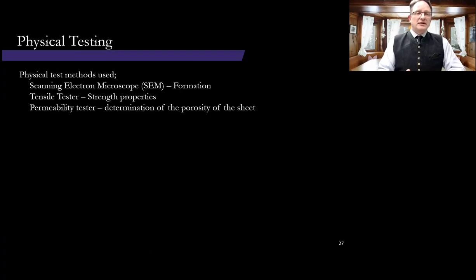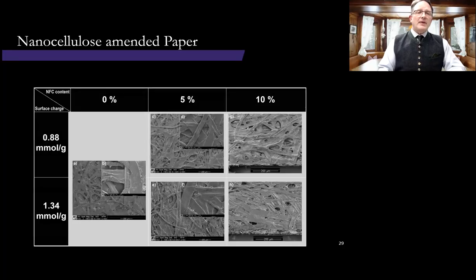With physical testing, for formation, we use scanning electron microscopy. For strength properties, we use tensile testing. And in order to determine the porosity of the sheet formed, we use permeability. So I'll summarize the results starting with formation. So in this image here on the left, this is a scanning electron microscope image of our base paper. And you can see fairly good formation, but it's fairly open, and not very densified.